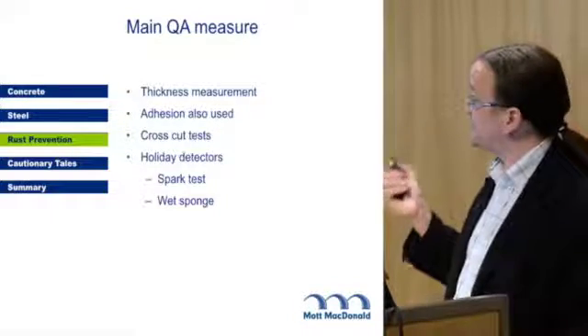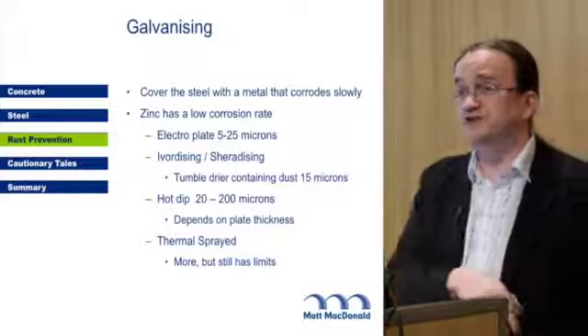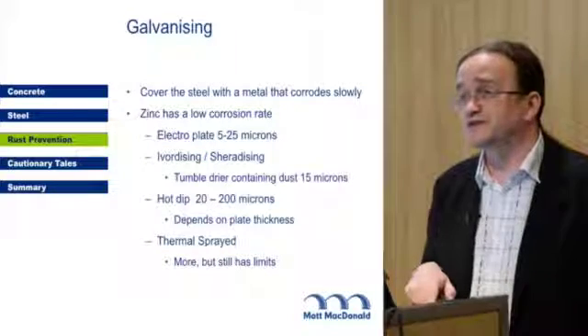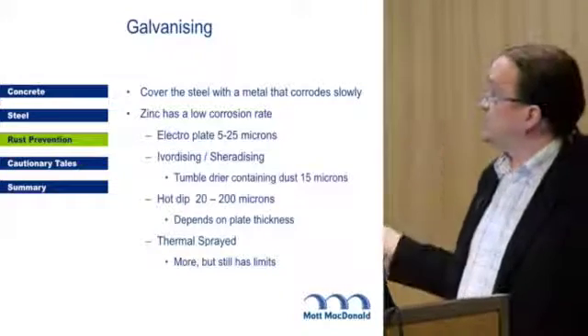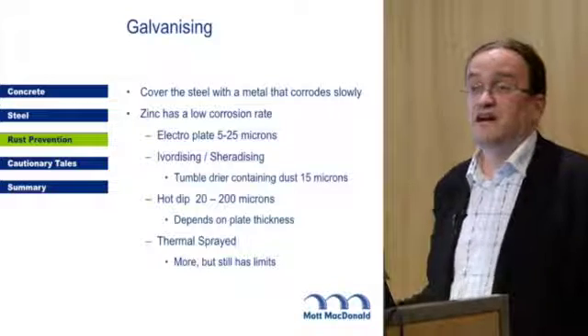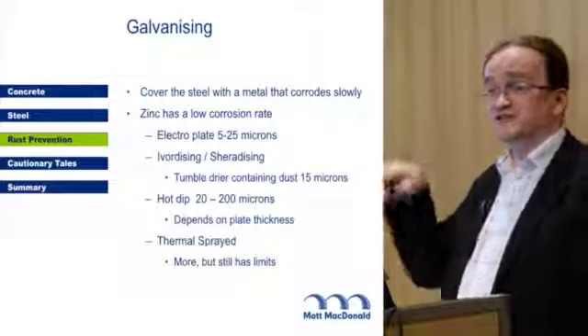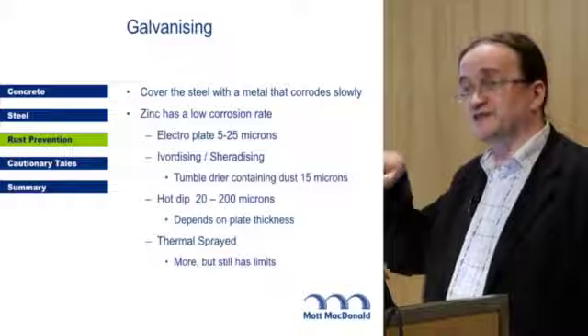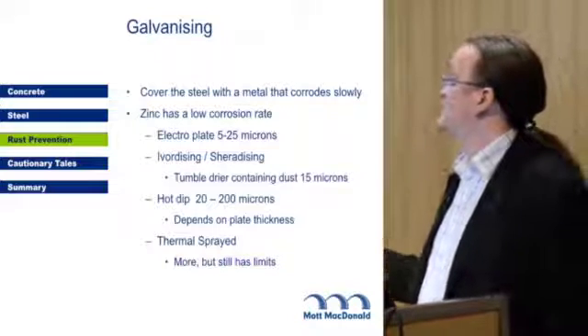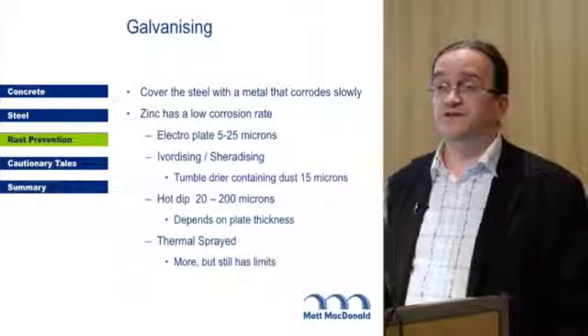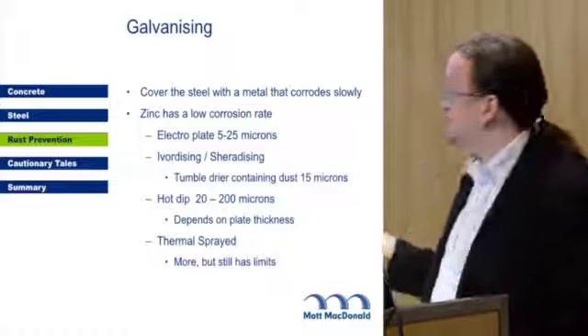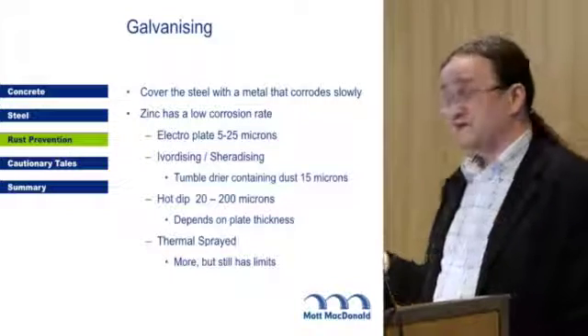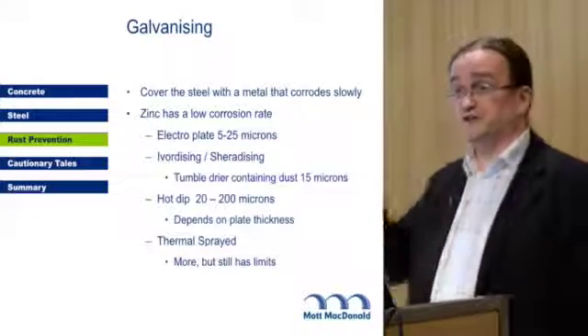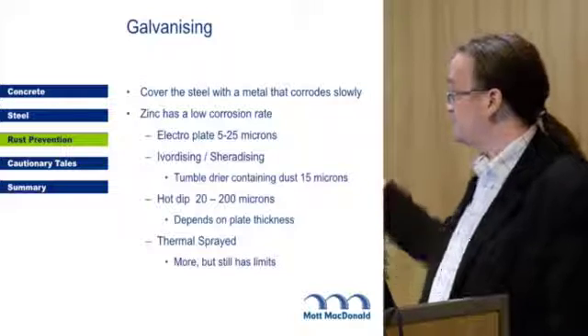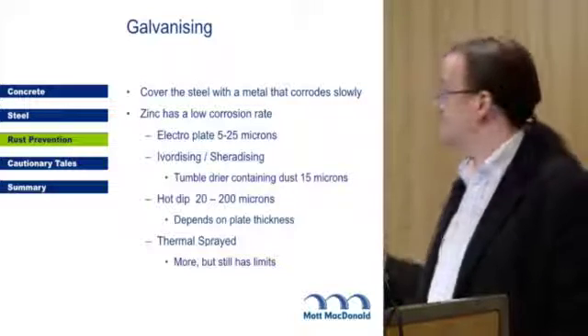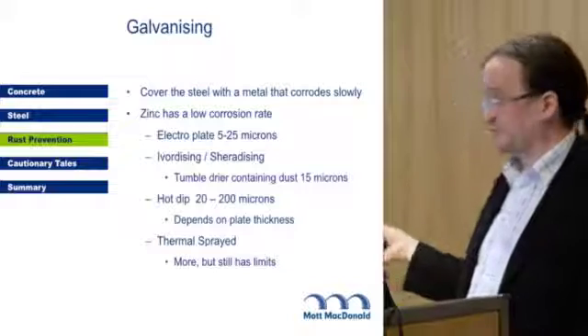That's paint. Galvanising: in the same way there are lots of different types of stainless steel, there are quite a few different types of galvanising. Basically, zinc corrodes slowly, and when you get a chip in the zinc, it's going to be an anode and locally protect the steel. Electroplating gives you about 5 to 25 microns of zinc. Sherardising, basically you stick a little bit in a tumble dryer full of zinc powder and you get 15 microns of zinc on it. Hot dip, you get 20 to 200 microns.